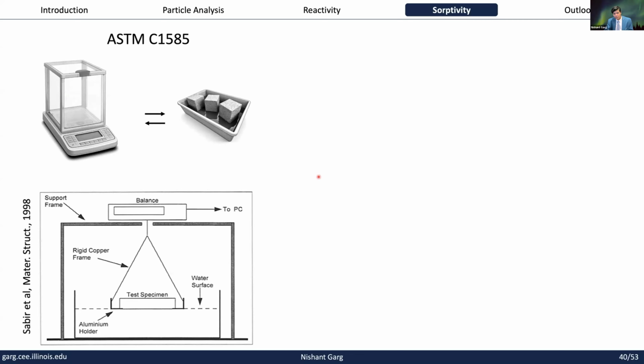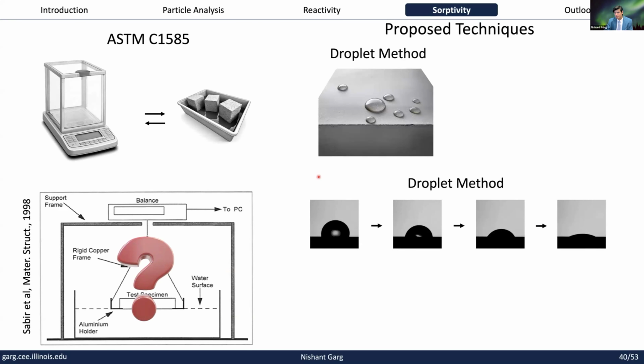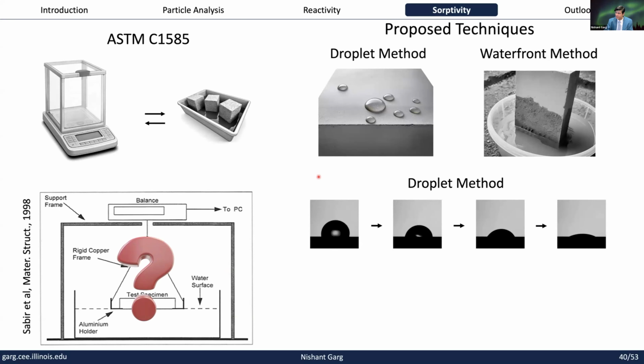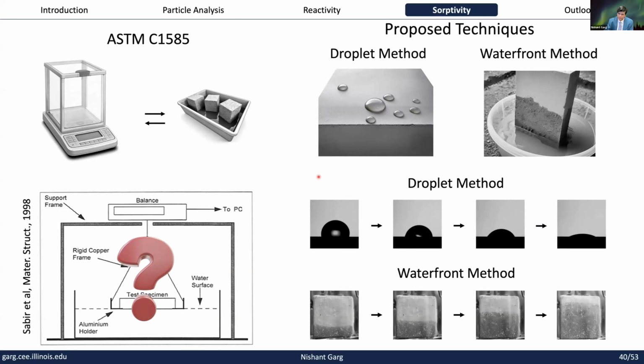By the way, there have been some approaches in the past where people use an automated balance to measure the weight change as the water is taken in. However, there have been some complications regarding the buoyancy that can change as the water is absorbed, and not everybody has access to this kind of automated balance. So what we thought of was two methods. One is the droplet method, and the other is the waterfront method, where the idea is to first place a droplet and see how much absorption happens. And then the second is looking at the waterfront itself as it moves through the sample.